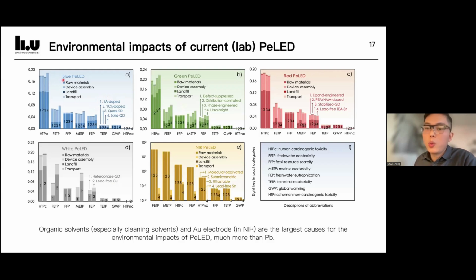And we also break down where the impact comes from, including raw materials, device assembly, landfill, and transport. So overall, RGB and white PeLED exhibit comparable impacts because of the identical device structure. The variation in material and electricity consumption for the transport layers or perovskite layer are insufficient to cause a significant difference. And the primary contributors of the impacts are raw material, particularly organic cleaning solvents like acetone or isopropanol. The remaining impacts come from the device assembly, pretty much from the vapor deposition process.